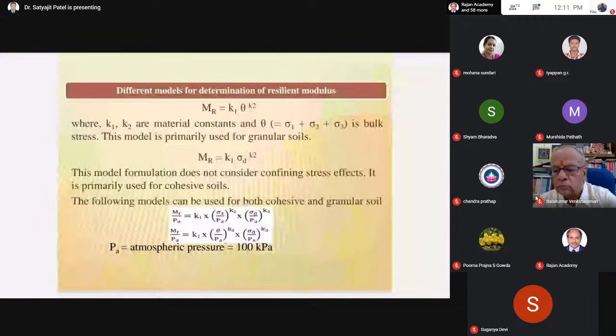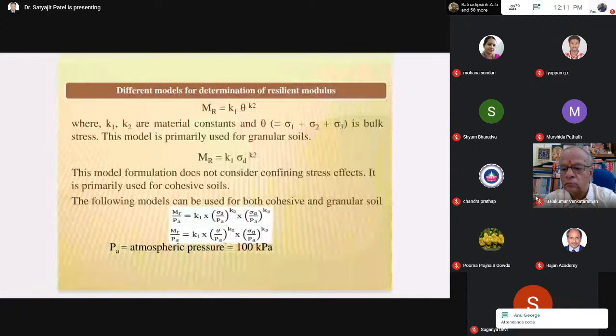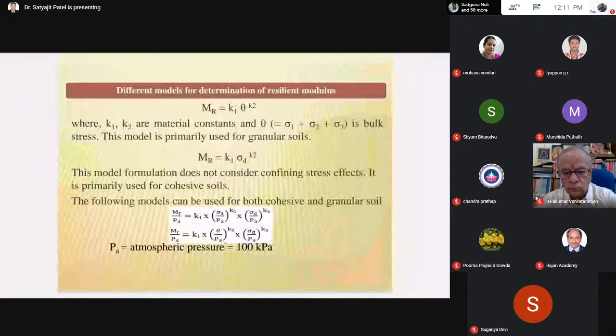From these 15 combinations, or 15 sets of MR and stress levels, we can find out these model parameters. After getting the model parameters for a given material, if you know the K1, K2, K3 values, you can predict the MR value for any stress combination. Besides the 15 stress levels for which MR is available, you can obtain the MR value for any stress level using these K1, K2, K3 values, which are a material property or constant for a given material.